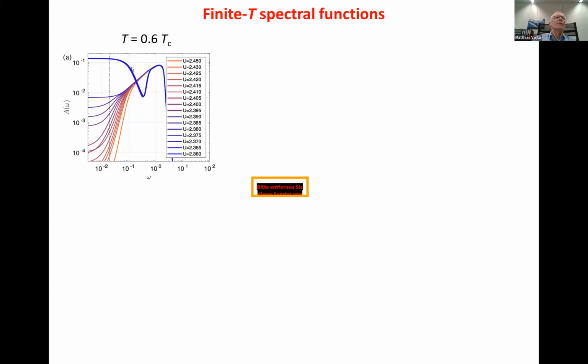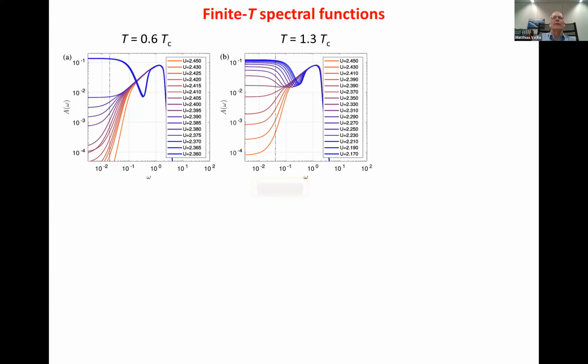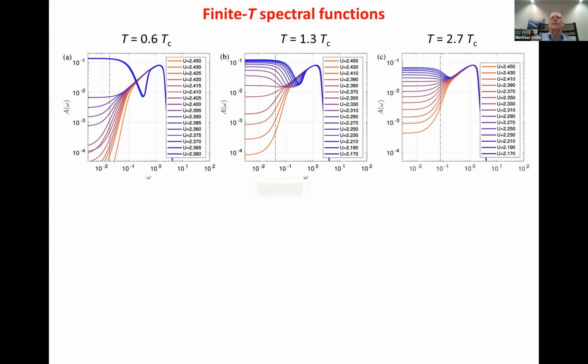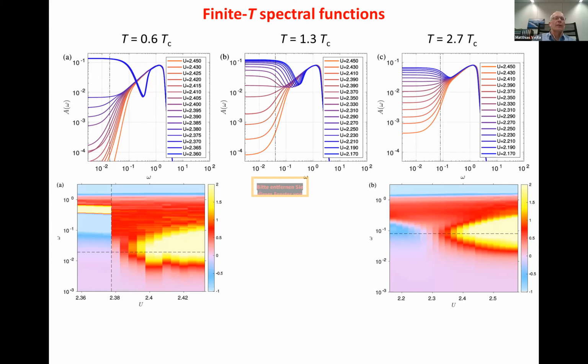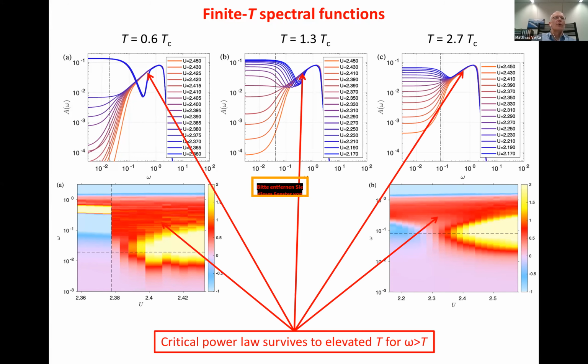Here you see power laws, and these curves which look strongly different are actually the ones in the metal. Recall there is a first order transition at low U towards an entirely different state. You can heat this up further and get curves like this - again color plots the same way, frequency and U with the effective exponent colored - and they all show a very nice power law regime, which gets somewhat narrower if you heat the system up, but there is a power law in this spectral function.